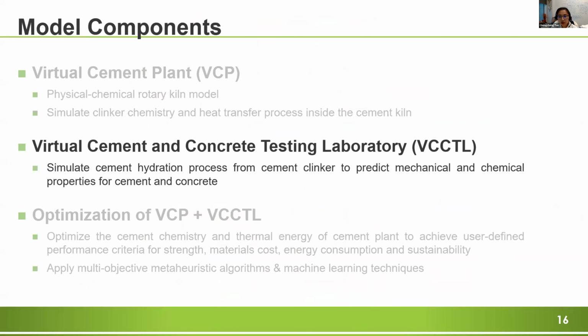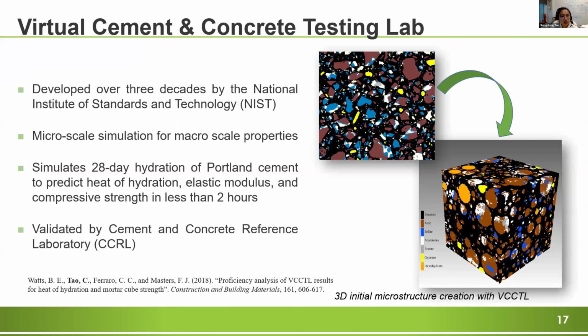The second part, the second model component, is called VCCTL. It's short for Virtual Cement and Concrete Testing Lab. It simulates the cement hydration process and predicts the material properties for cement and concrete. So the VCCTL is software developed by NIST. It simulates the cement hydration process and predicts the chemical and mechanical properties for cement and concrete, such as the modulus for 7 days and 28 days, heat of hydration, and compressive strength.